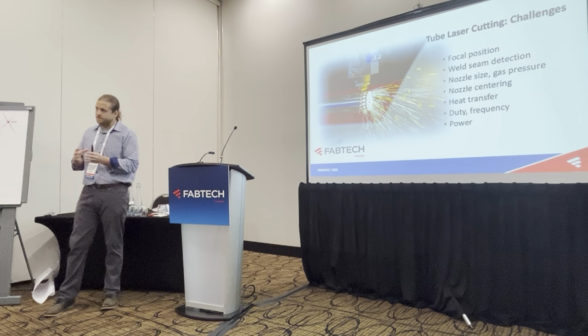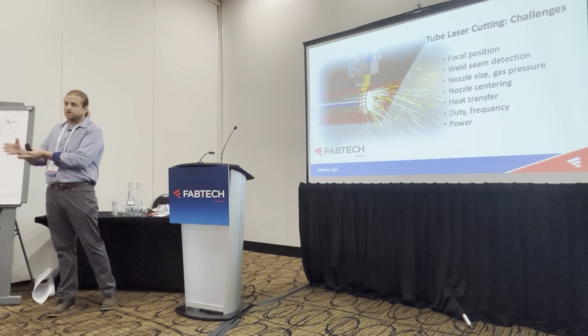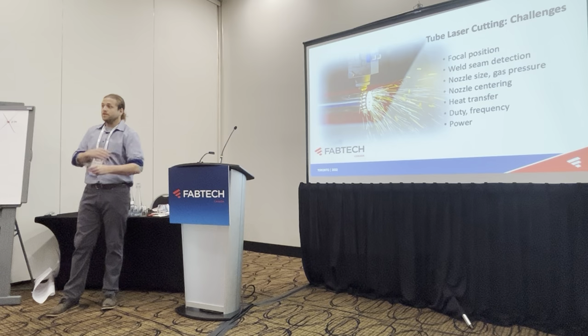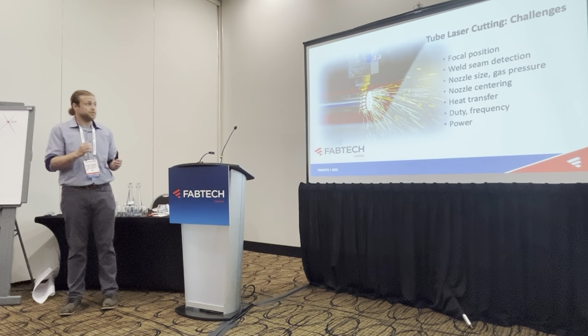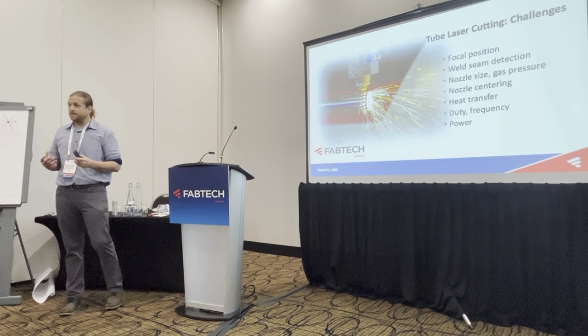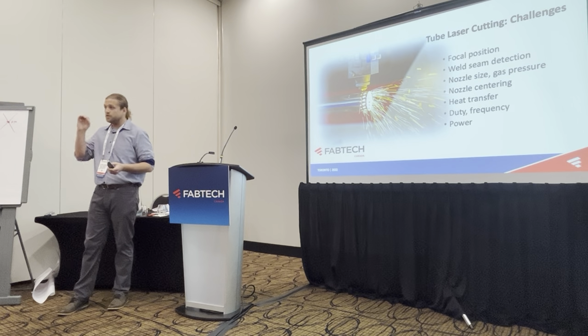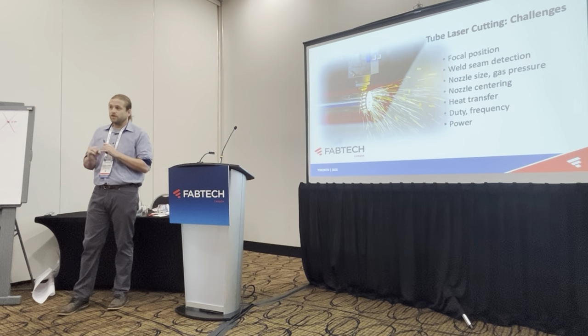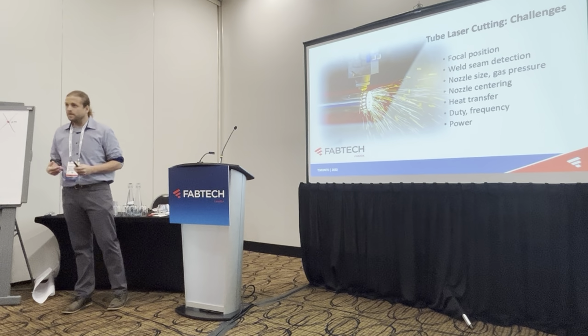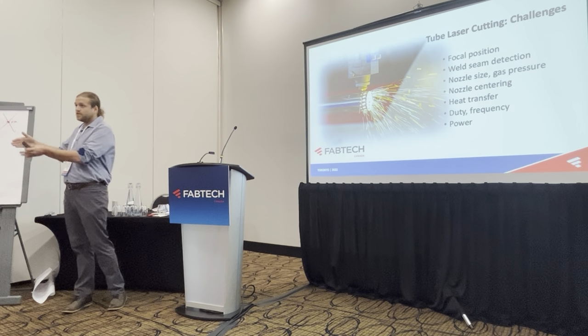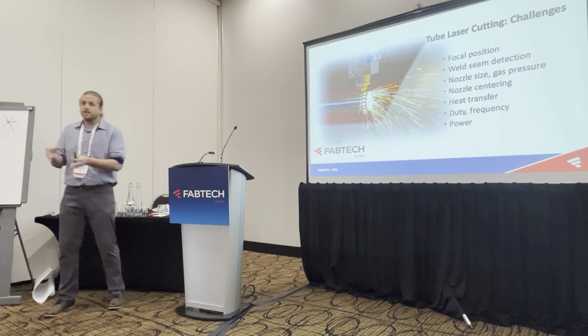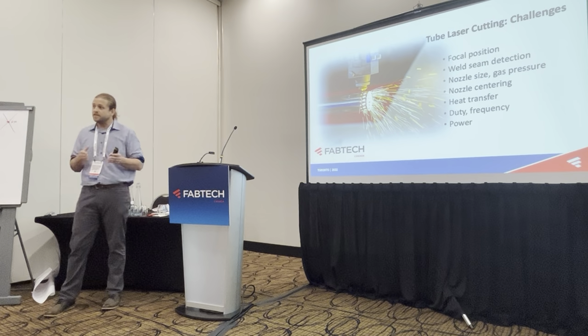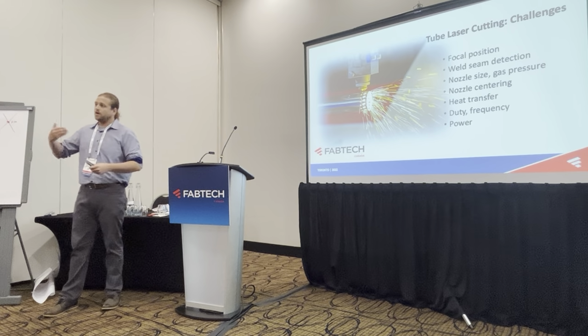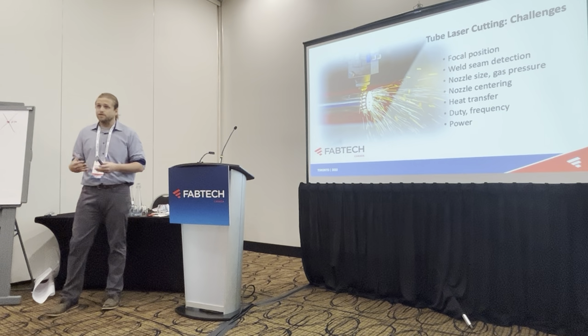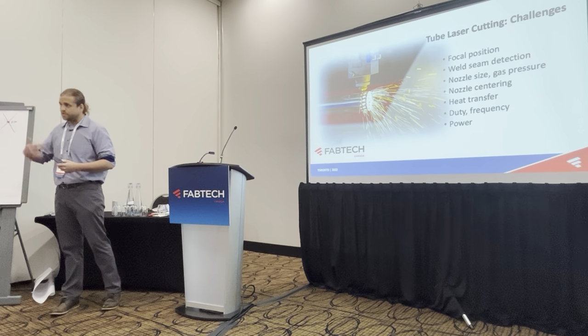So it holds heat, and as that transfers down the tube, you start to lose your cut. And you can run into serious cut quality issues. I've had it in the past where we've taken on work where it's one inch OD, 150 wall, mild steel, very, very small cross section, with a lot of heat to cut that thick wall. First 20 or so parts cut really nice, but as that heat continues to transfer and it's not dissipating as fast as the heat is increasing, your cut quality starts to degrade. And the next thing you know, you're not cutting the material, you're actually welding it shut.